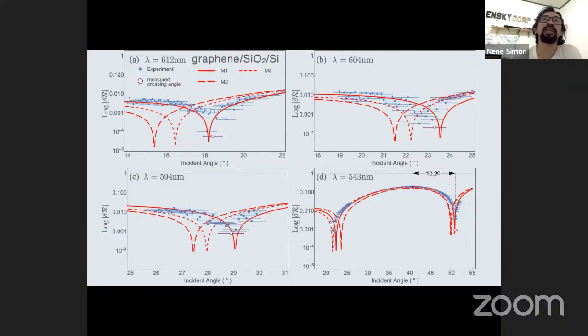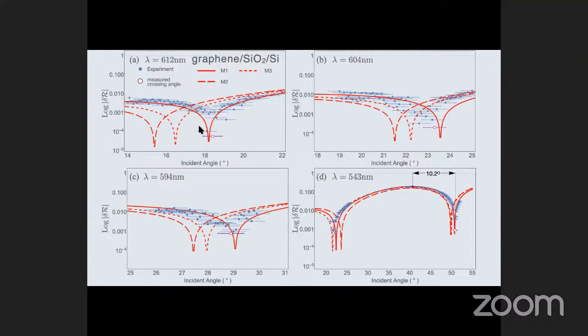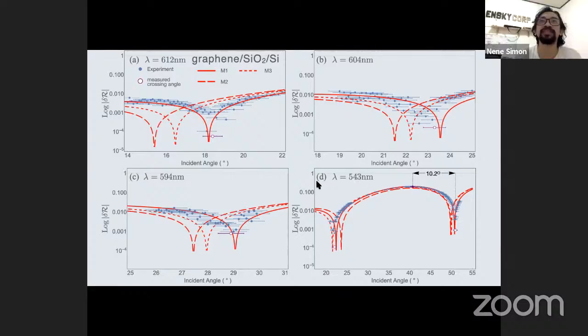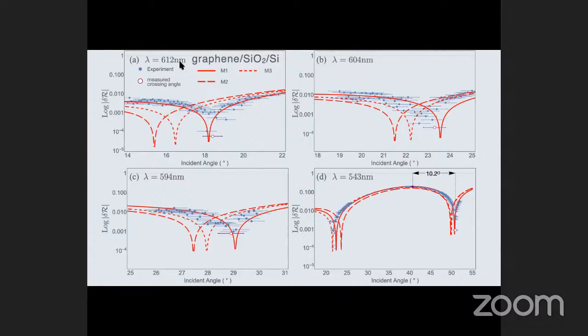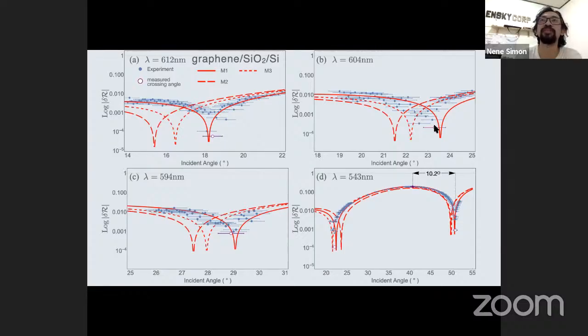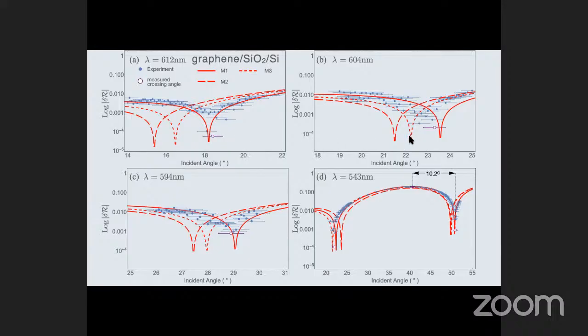So now, is there water vapor on top of the sample? I'm not really sure about it. But to give you an insight, if the water vapor would change the position of the crossing angle, then most likely our result won't be consistent with different wavelengths. Actually, crossing angle measurement can be done with just a single wavelength. But to show the consistency of our measurement, we performed the crossing angle measurement with different HeNe wavelengths. The consistency of the result shows that even if there's a water layer on top of our sample, it's not affecting our system.